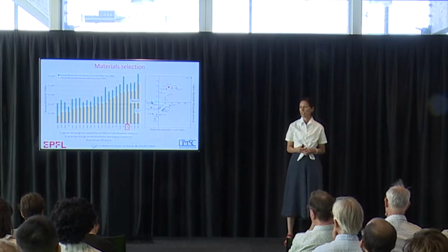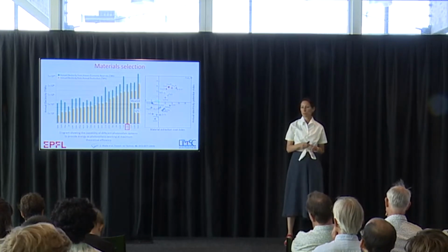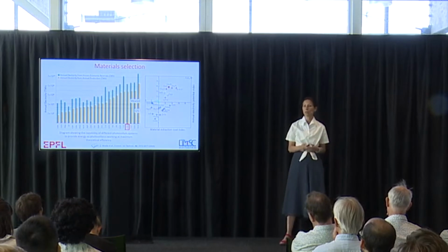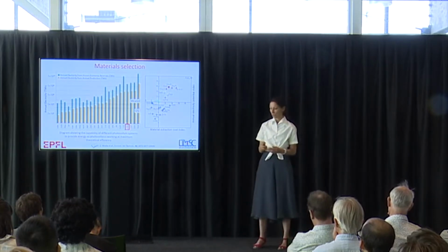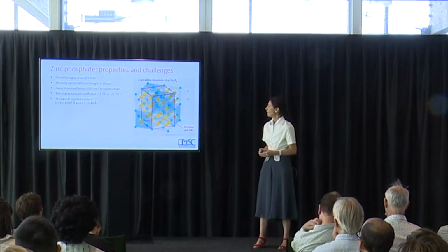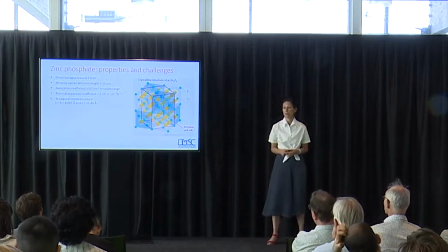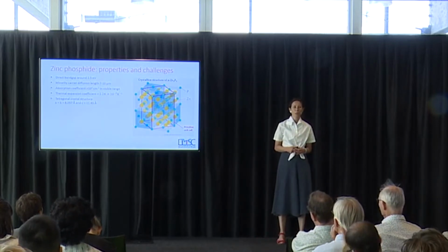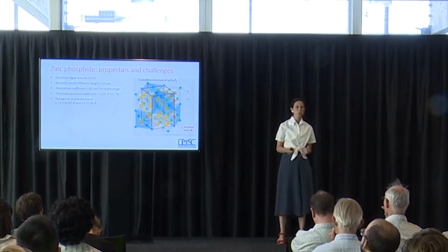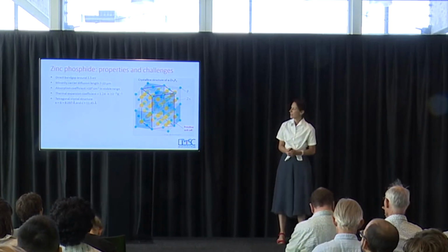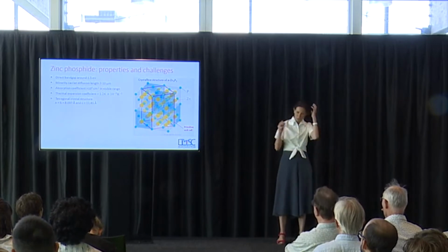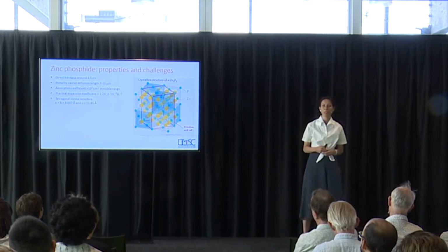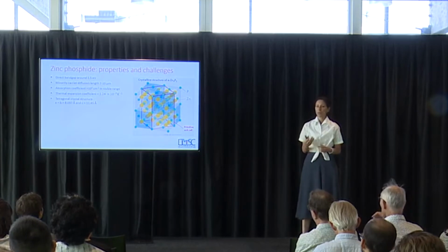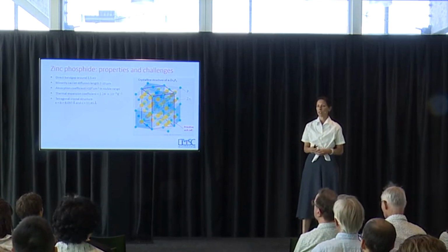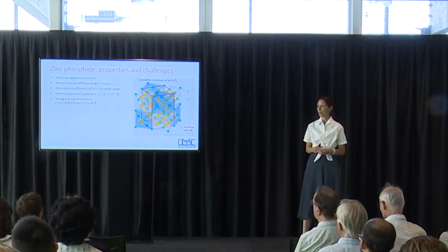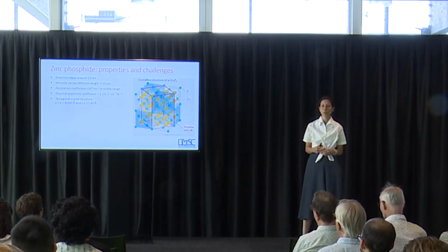We understood the challenges, but we thought we could go around them because science evolves, and we thought that the challenges that have been raised in the past are not a challenge in work today. So this is the crystalline structure of zinc phosphide. It's a tetragonal structure, which is very different to what we were used to. We were used to cubic materials, so this is fun, and sometimes you have to scratch your head to understand what's going on when you have a TEM. It has a good carrier mobility. The diffusion length is long. The band gap is 1.5 electron volts, so everything looks good for this material to make a solar cell.